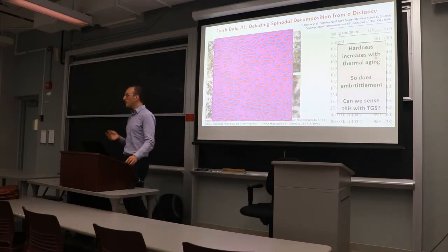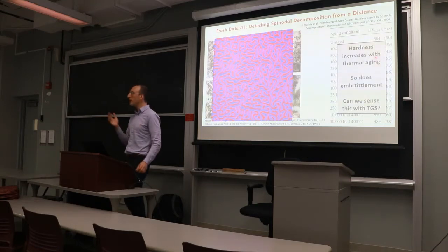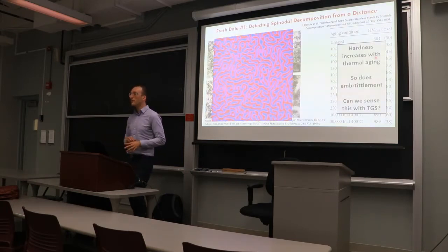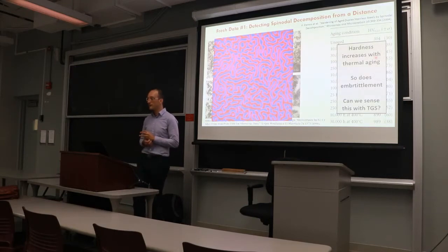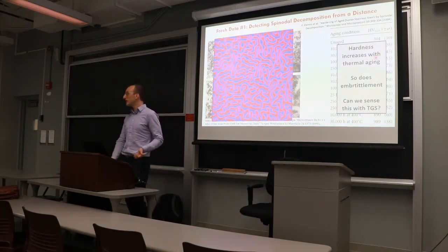And if we have a way of measuring spinodal decomposition without cutting a piece of material out of a reactor, like literally cutting a hole the size of a golf ball out of the core barrel and making a test specimen, we'd have a way to be more sure about reactor life extension. So we threw TGS at this. My hypothesis was spinodal decomposition should change the thermal diffusivity of that phase decomposing. I was wrong, but we looked anyway, and we found something we didn't expect.